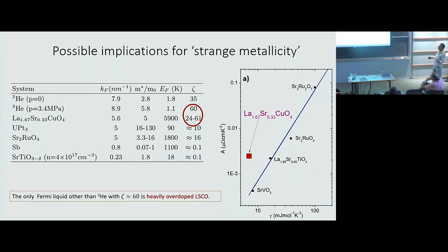If you don't want all this story, you begin by plotting the Kadowaki-Woods plot for all metallic perovskites. These are 2 experimentally accessible numbers: the prefactor, which you can measure from resistivity, and the specific heat. All these guys are on the same line, and this one, the Fermi-liquid one on the heavily overdoped side, is clearly out of range. So is this a coincidence? In this case, even if it is a simple Fermi surface, it has a strong anisotropy, so you cannot make the same comparison. If there is any zeta, it is different for nodal and antinodal quasiparticles.